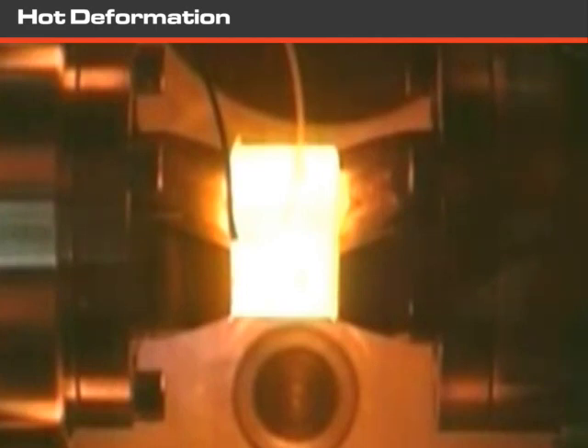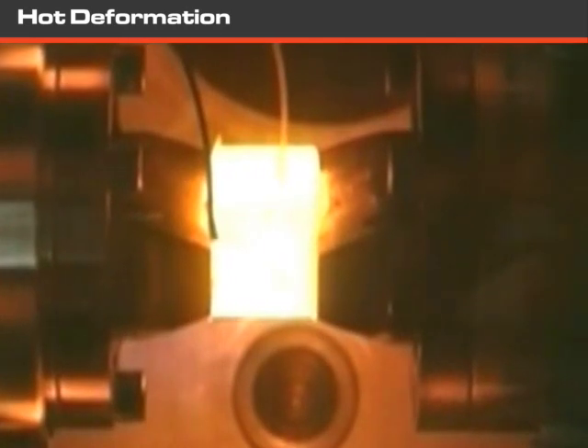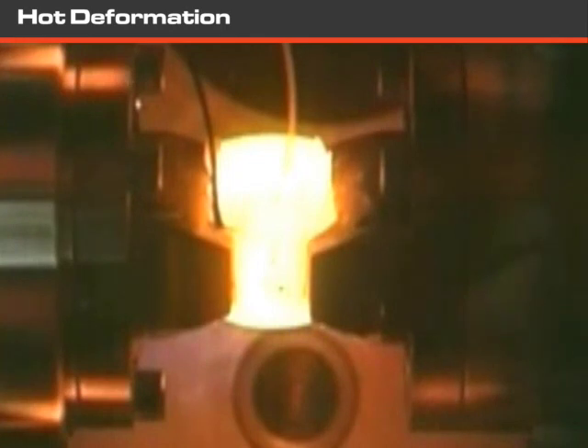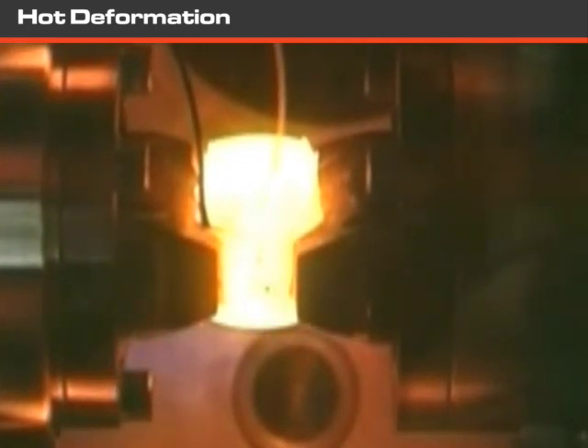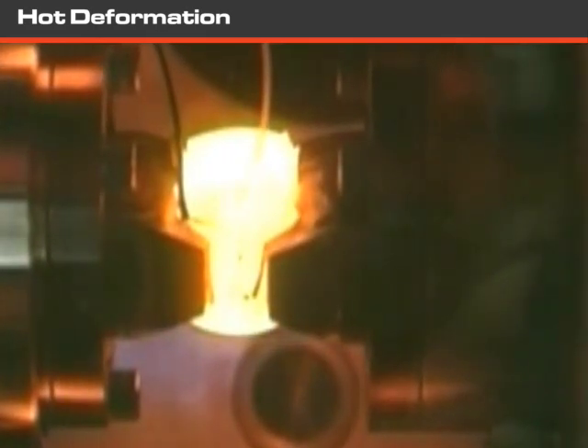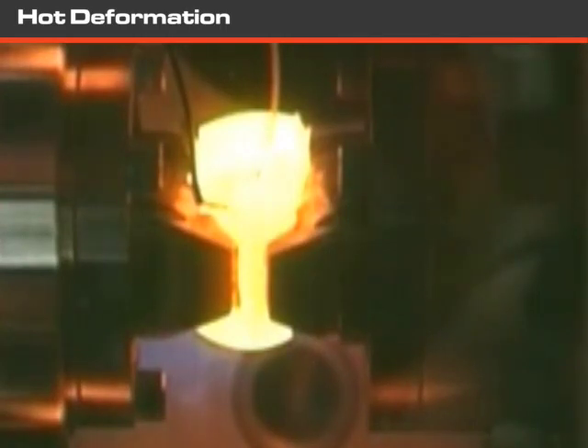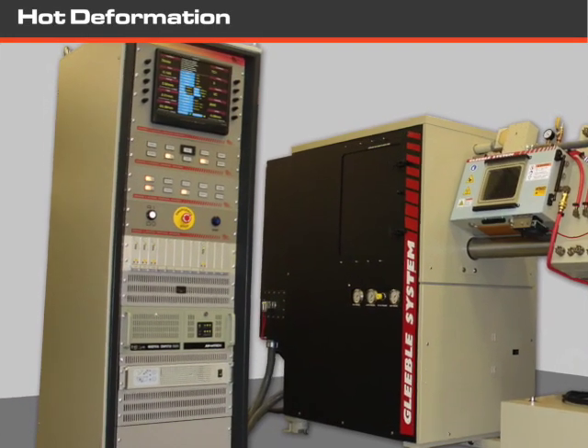During this multi-hit simulation, notice that both anvils move, each at the programmed time. The left and right anvils move to position the specimen before the first hit. The left anvil hydraulic system compresses the specimen, finishing against a mechanical stop to achieve the programmed stroke rate. Since this yoke stops the left anvil instantly, there is virtually no deceleration curve at the end of the compression and no other travel, permitting high strain rates. The right anvil hydraulics reposition the specimen so that the amount of compression during the next hit provides the correct strain. The entire process takes place under computer control with closed-loop feedback control of all variables.